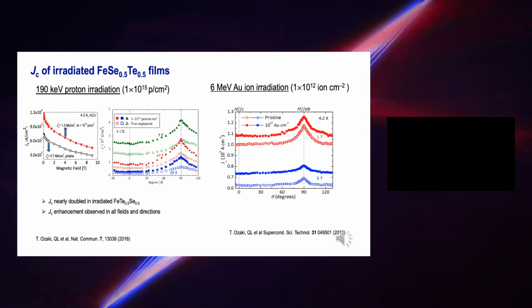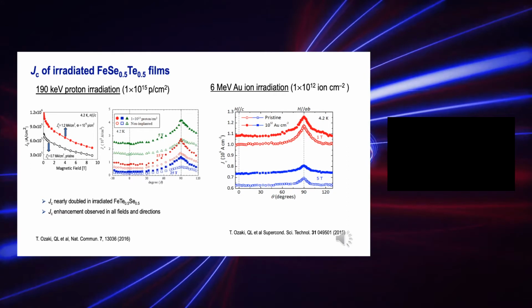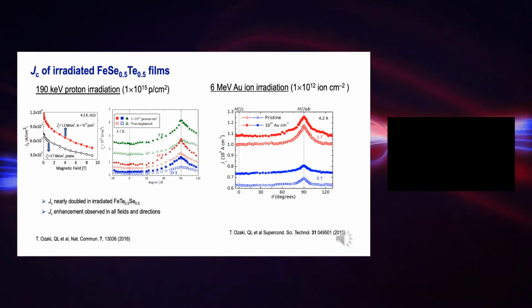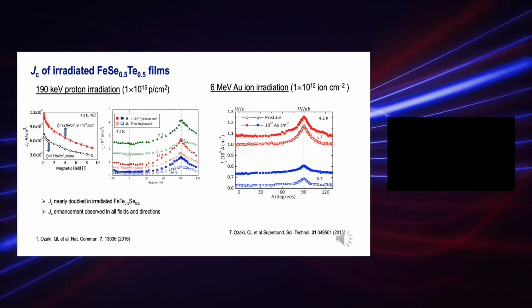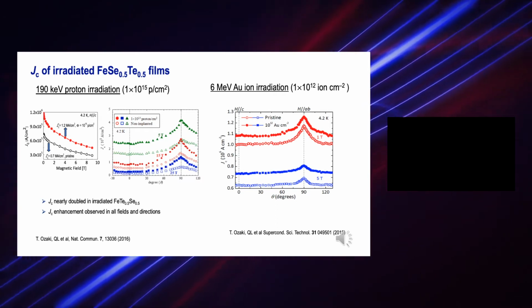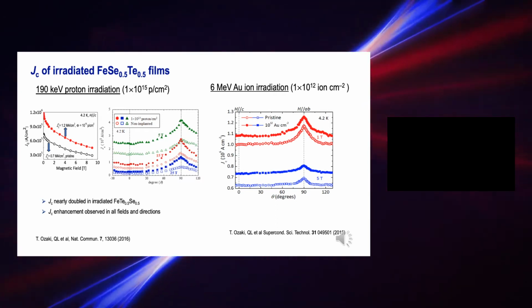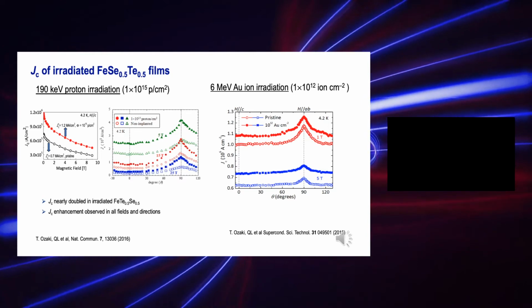Now, this enhancement was also observed with 6 MeV gold ion radiations at a dosage of 10 to the 12th ions per centimeter square. This is represented in the figure shown on the right-hand side, taken at 4.2 Kelvin.